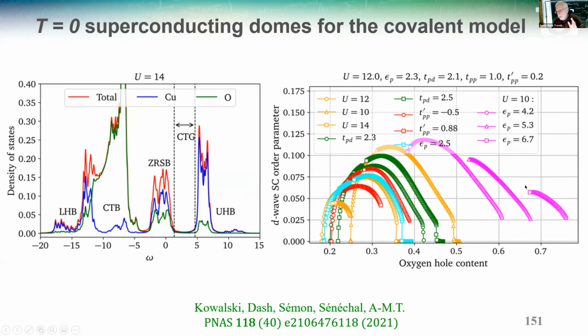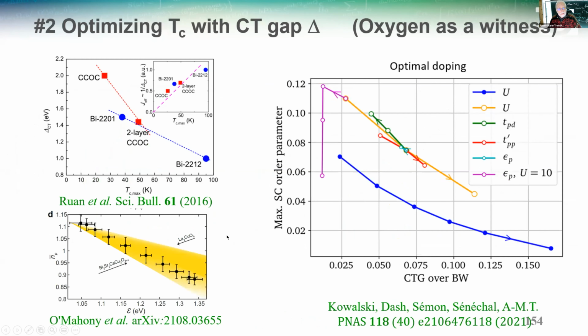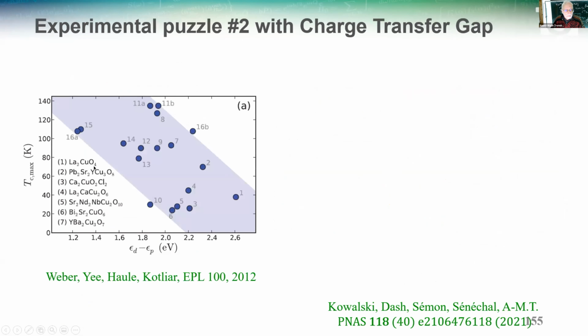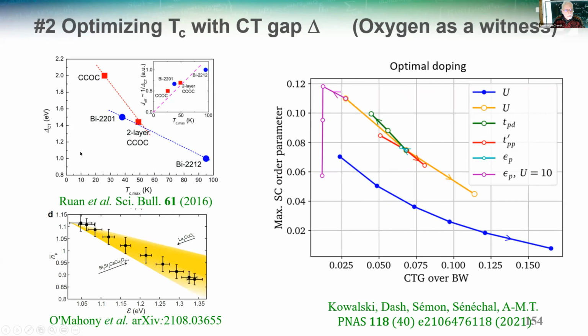Now you see what's happening here: this is going down. What happens is that this charge transfer gap is closing. When the charge transfer gap is closing, we have to go to this weak correlation picture, and indeed, the TC goes down. Another way to optimize TC is with the charge transfer gap. If you look at these experiments that measure the charge transfer gap as a function of TC max, you see that the larger TC corresponds to a smaller charge transfer gap.